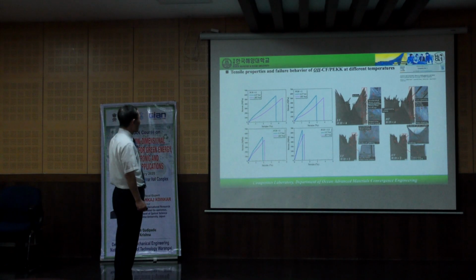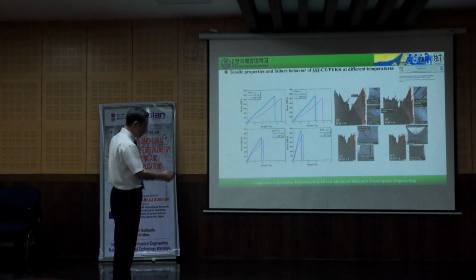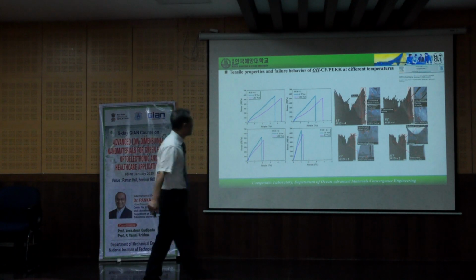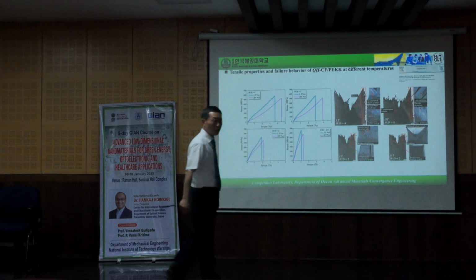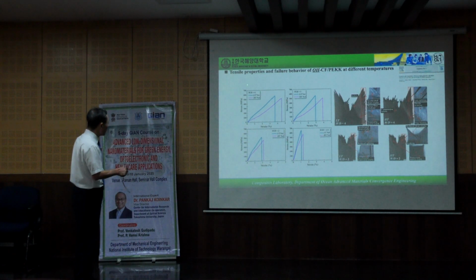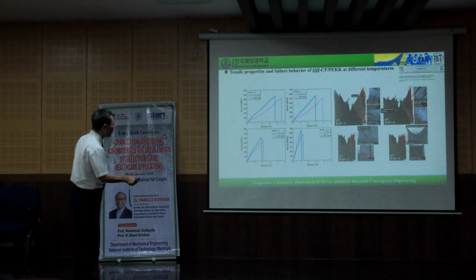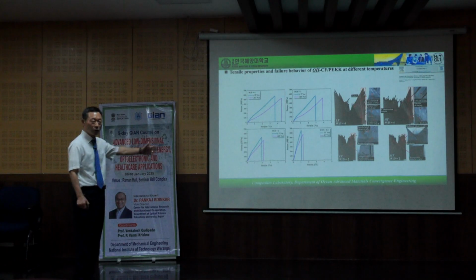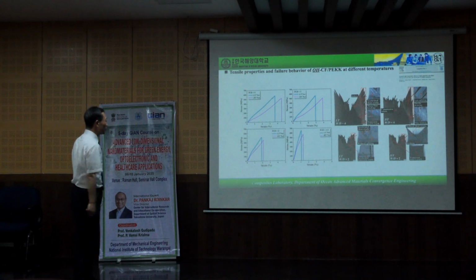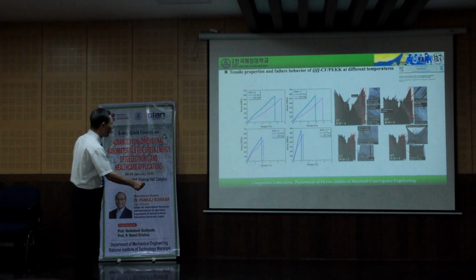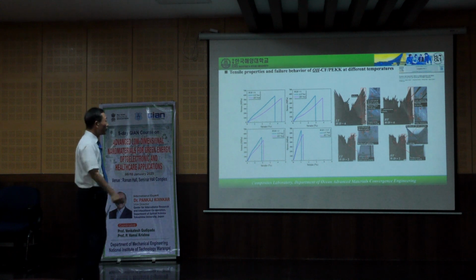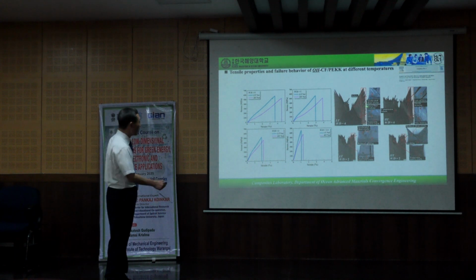This slide shows the tensile properties and the failure behavior at different temperatures. Also, we published in Composite Part A journal. We changed the W by D ratio from 4 to 1.5, 1.5 to 4. So just compare those behaviors. In case of 1.5, the behavior is like this, small strain, and 2, 3, 4, at low temperature and high temperature. The fracture morphology will be changed like this.